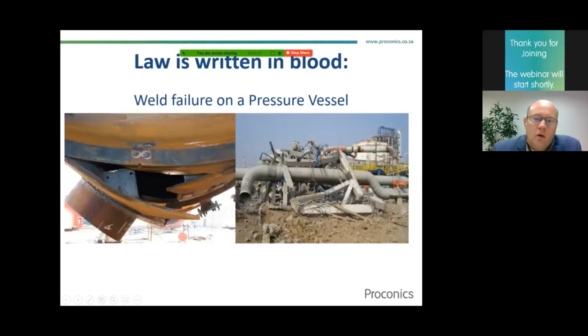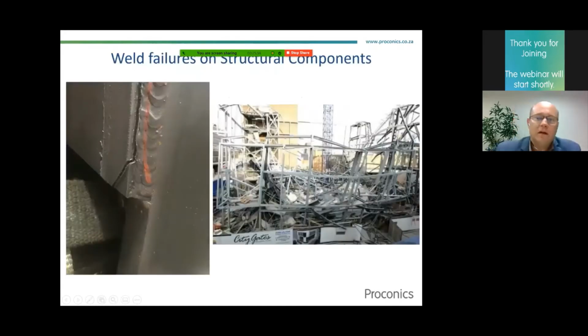So law is written in blood. The reason for this is that laws and standards are based on past experiences and failures and possibly fatalities of human lives. As you would see in the picture on your left-hand side, this is a vessel that erupted due to weld failure and caused the whole process plant to collapse and also caused fatalities. So weld failures don't only occur on pressure equipment, they could also occur on structural components. As you would see here, this is a failure of a structure weld that could cause a whole structure to collapse and also take human lives.